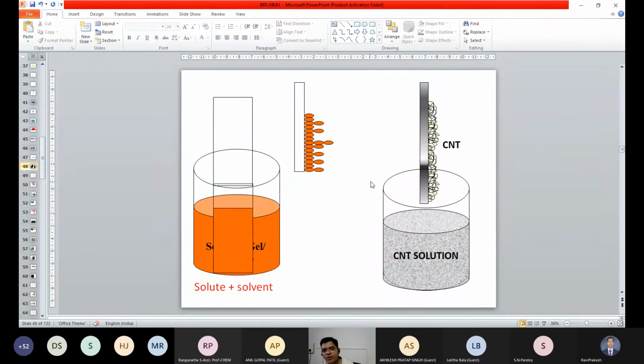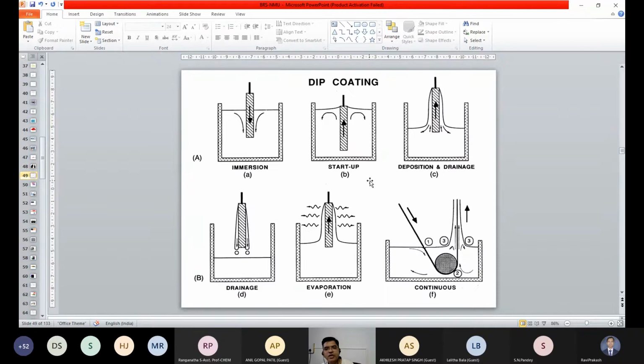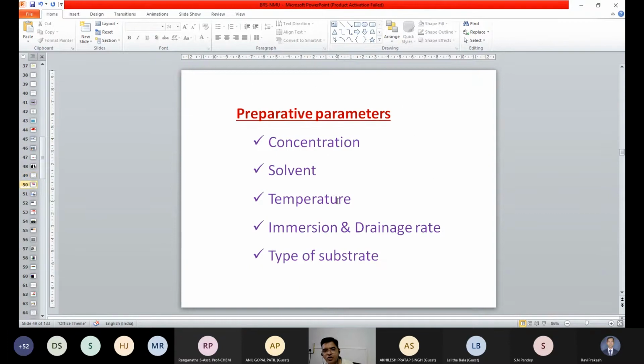And depending upon the number of dips and how you are drying, that plays a very important role, so that you can alter the thickness of the carbon nanotube on the substrate surface. So here, that is simply dip and dry coating: how you are immersing, how much drainage rate there is, how much evaporation rate there is. That changes the property of the carbon nanotube.